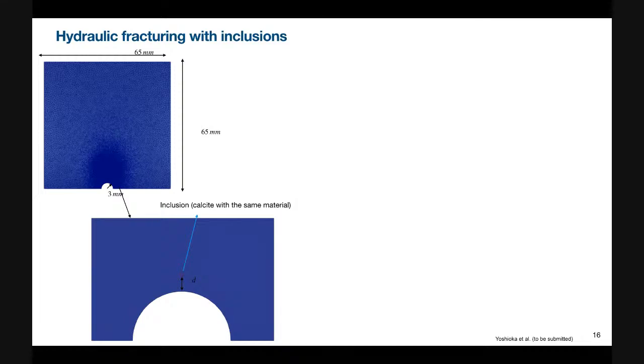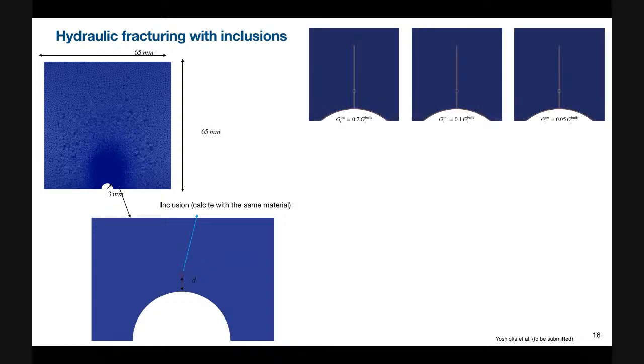So we set up a wellbore and took a half symmetry. Then we placed an inclusion some distance away from the borehole. This inclusion has the same material properties, but the interface toughness is weaker than the bulk material. We considered different interface strengths of the inclusion. In the first case, the interface has only 20% of the strength of the bulk material, here 10%, and 5% here. In all the cases, the hydraulic fracture just propagated straight, ignoring the inclusion. So it penetrates the inclusion.